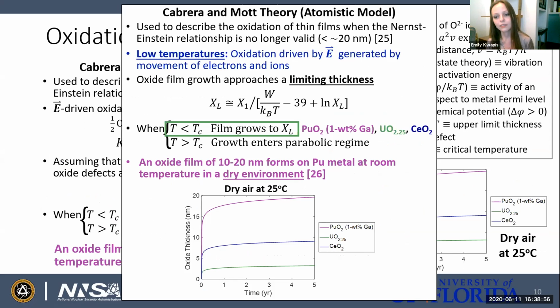describe the oxidation, which is driven by the electric field generated by the migration of electrons across the metal oxide interface. And the general conclusion here is that the oxide film is going to approach a limiting thickness as long as the ambient temperature is less than some critical temperature, which is related to the activation energy of the oxidation reaction. And for the three elements I've chosen to show here, they all satisfy this condition.